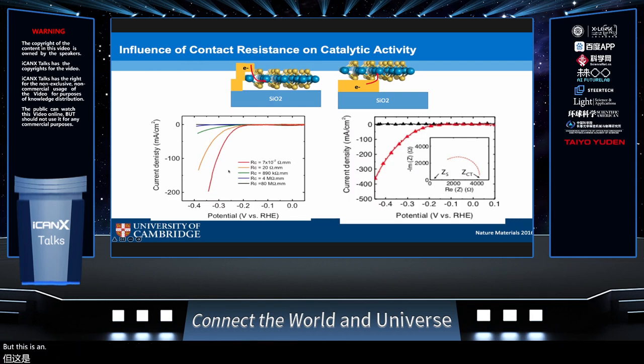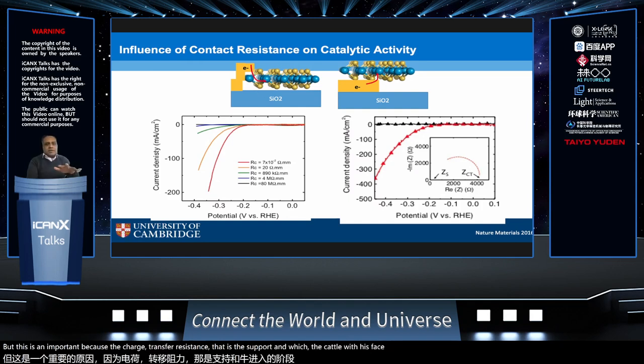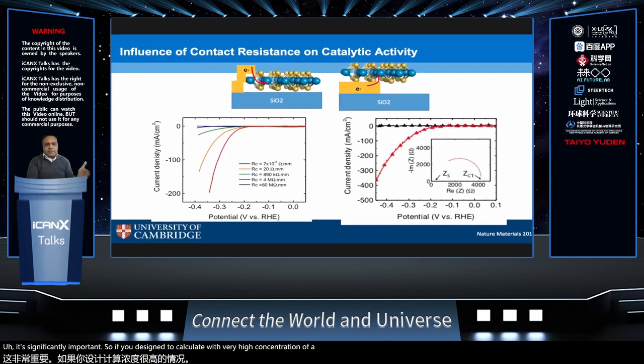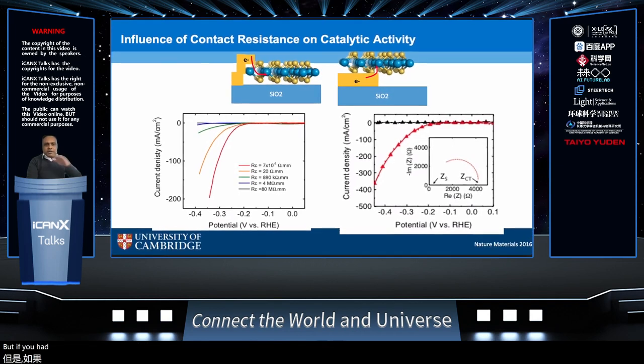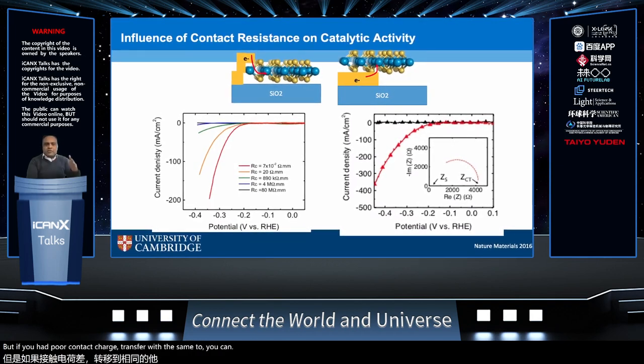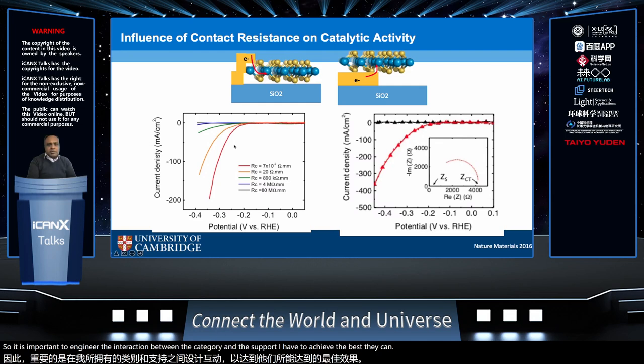But this is important because the charge transfer resistance, that is the support on which the catalyst is placed, is significantly important. So if you designed a catalyst with a very high concentration of active sites, but you had poor charge transfer, or very high resistance between the catalyst and the support, you would have this bottleneck in the catalytic activity. So it is important to engineer the interaction between the catalyst and the support to achieve the best catalytic performance. Otherwise, there's a bottleneck in the series resistance.